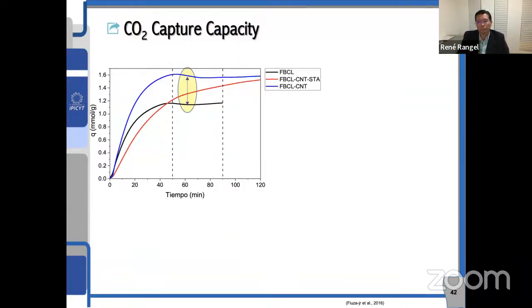Okay, here are some results. This is at atmospheric pressure and 25 degrees Celsius. If we compare the black line with the blue line, the blue line is the material that has the carbon nanotubes. We already increased the absorption capacity from about 1.1 to 1.5 millimoles per gram, which is very good, and this is related to surface area. Kinetics is very fast, as you can see, because some materials can take hours and hours to reach equilibrium. In this case, in a few minutes, you saturate the material.